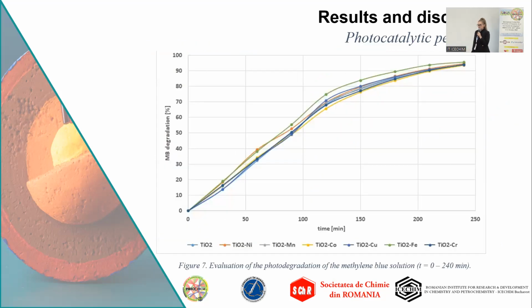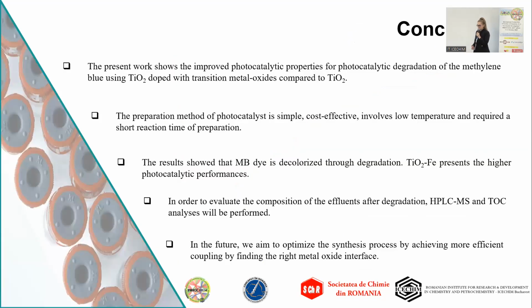The evaluation of photodegradation of methylene blue solution was recorded and is presented in Figure 7, where titanium dioxide doped with iron presents the best results for photocatalytic degradation, because it registers the best obstacle for the recombination of electrons and holes.